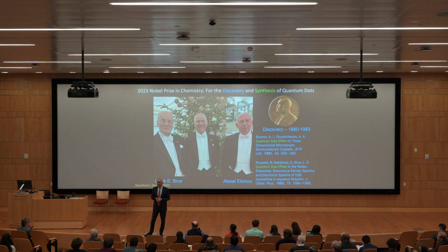And in one of the flasks, the particle started to grow. And this beautiful color appeared, and I took an X-ray diffraction, and it was really crystalline. It was this beautiful sample. And for the first time, we could actually start to see emission coming out of this. Before, we didn't see any emission because it was full of defects. The electron wave was finding a defect and losing its energy through non-radiative means. So, I got a sample and I started to do physics on it, and it was interesting.